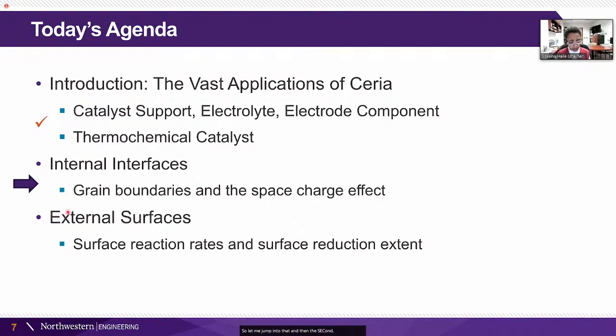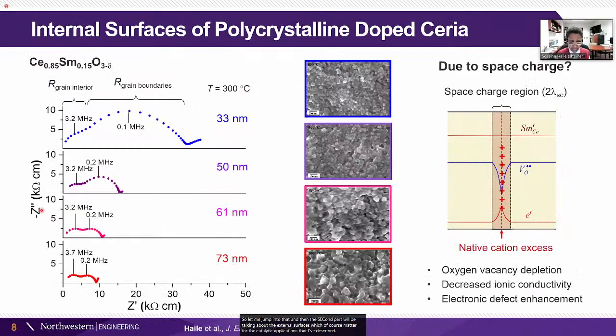And then the second part will be talking about the external surfaces, which of course matter for the catalytic applications that I've described. Here is an example showing the influence of the grain boundaries in the bulk region of the electrolyte. What we've done here is create materials with different nanostructures, so different grain sizes, between 33 and 73 nanometers. And what you can see is that with the smaller sizes, the more nanostructuring, the larger the impedance overall.